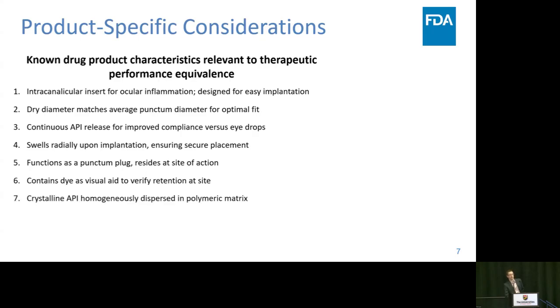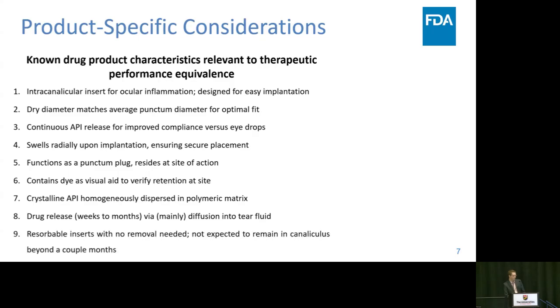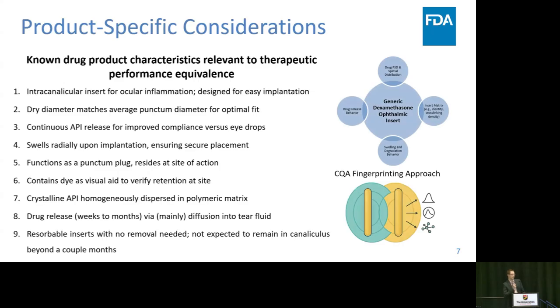And then it contains a crystalline API that's homogeneously dispersed in the polymeric matrix in particulate form. And the drug release happens over a long duration, from weeks to months, mainly through diffusion into the tear fluid. And then finally, these are resorbable inserts that don't need an active procedure to remove. They'll just resorb and degrade over time. It's not expected that they remain in the canaliculus beyond a couple months, depending on the chemistry that's used to make the cross-linked hydrogel.